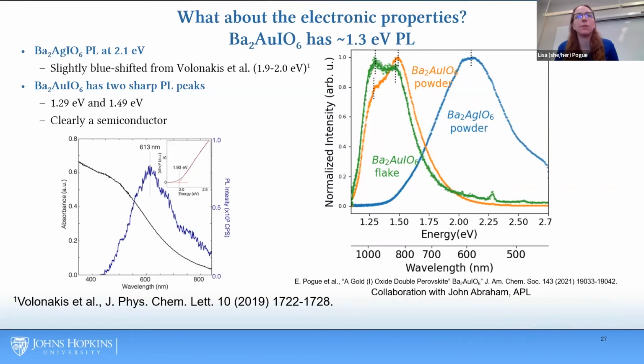As you can see here, the barium gold periodate band gap is well matched to the solar spectrum, and the barium silver periodate band gap is also relatively low for a double perovskite material. And so these could be useful with improved synthesis that doesn't leave behind the hydronium.